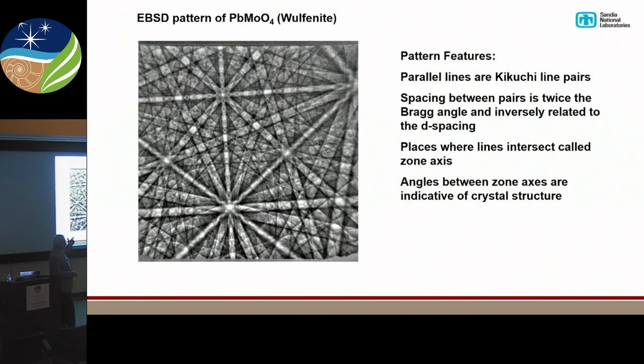One can look at that and really start to understand the crystal structure if you know what you're looking at. So what we have here are these parallel lines. Those are the Kikuchi bands. The spacing between those is twice the Bragg angle, right? So we can measure something about the d-spacing, although you'll notice the edges of the bands are not quite sharp, and so it's not very accurate.